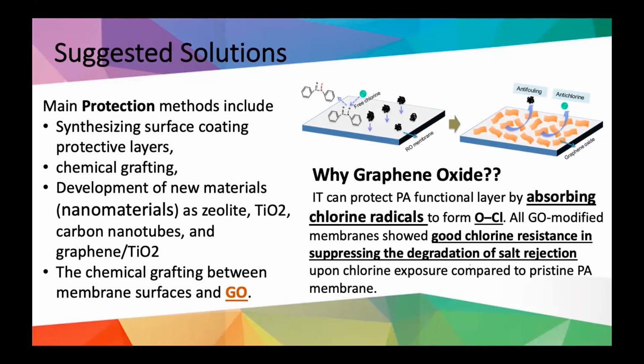So our suggested solution is to synthesize or get some surface coatings which give a low-cost membrane. This is one of the goals of our project: a low-cost membrane composed of developed nanomaterials, zeolites, titanium dioxide, carbon nanotubes, and graphene oxide, complexed with any other way. We benefit from chemical grafting to increase the contact between the graphene oxide and the membrane, and to get benefit from this graphene oxide.